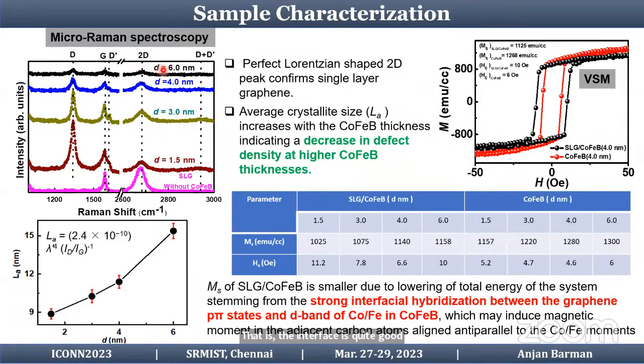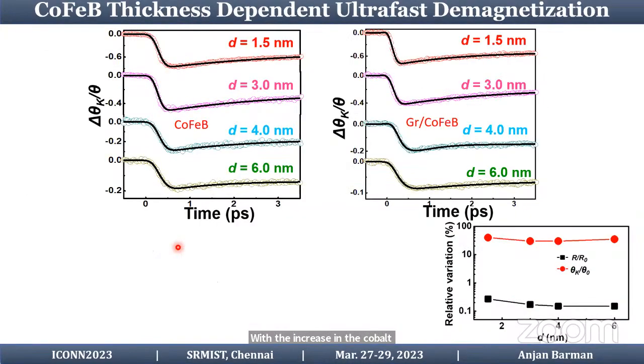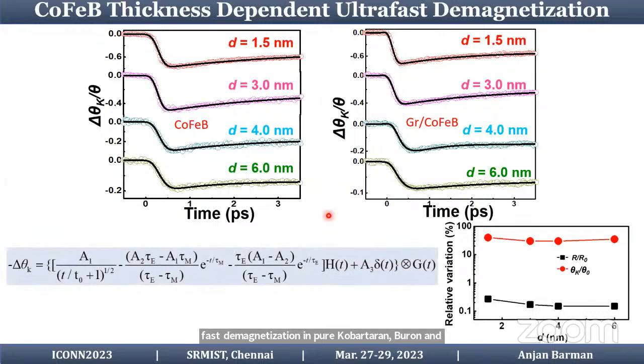The Raman experiment shows that they are purely single layer graphene with a defect peak, which actually shows that the defect density increases with the increase in the cobalt iron boron layer thickness. So there would be an effect of that, and we'll try to study it. So we first studied the ultrafast demagnetization in pure cobalt iron boron and graphene cobalt iron boron, and these are the data and these are the fit using this expression.